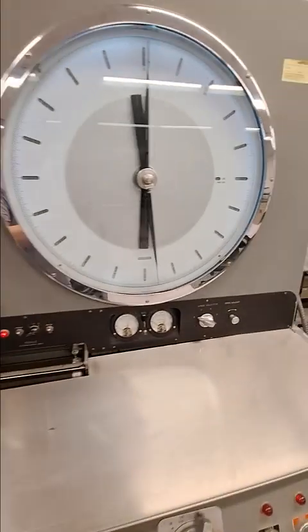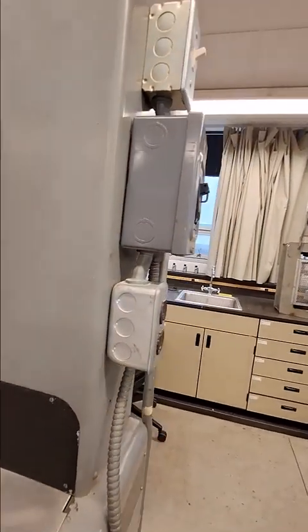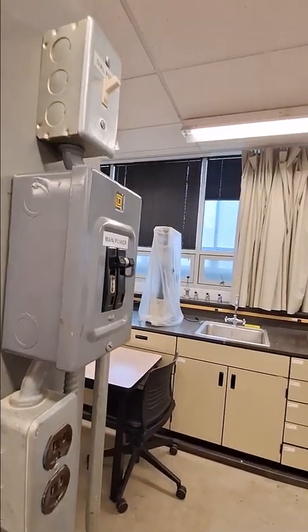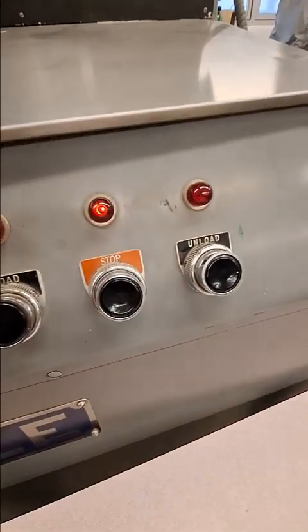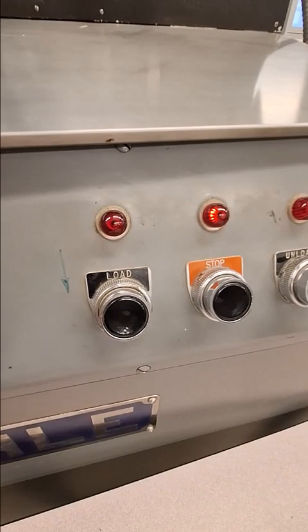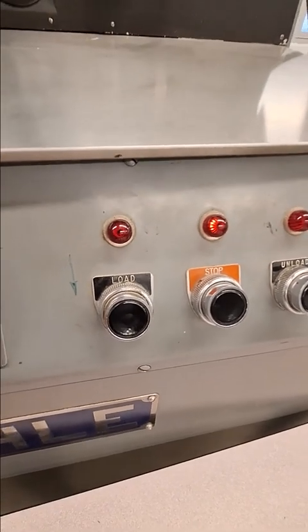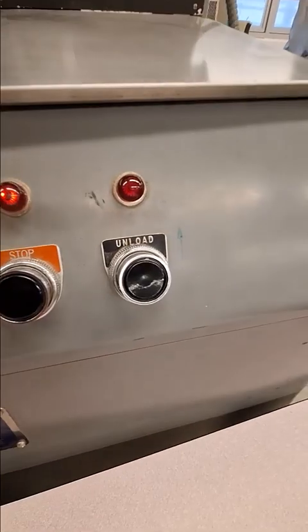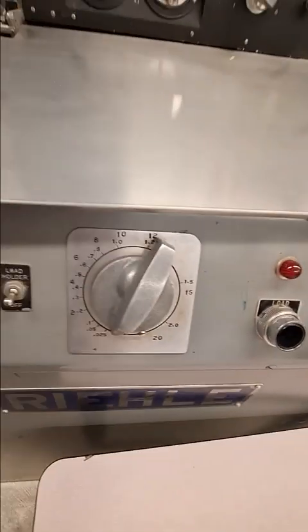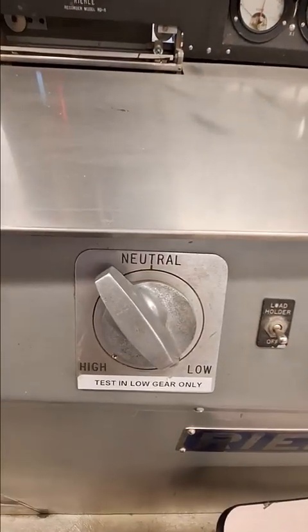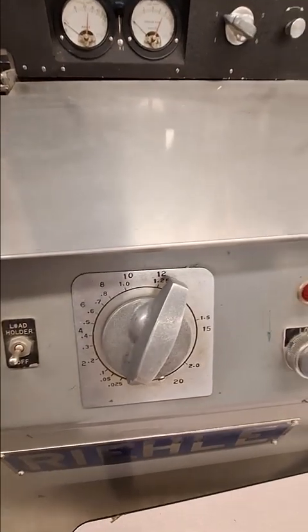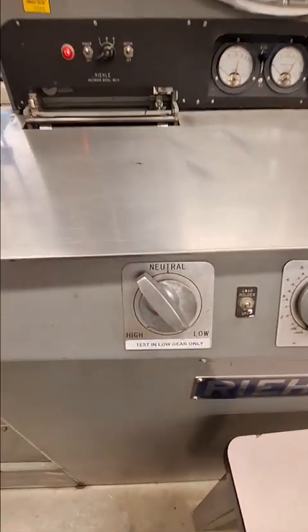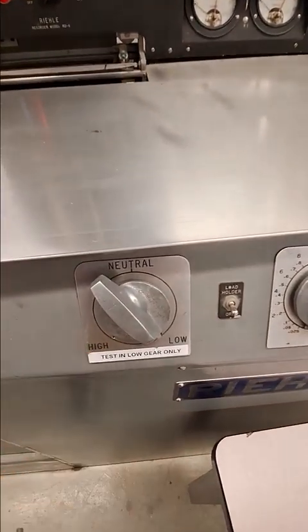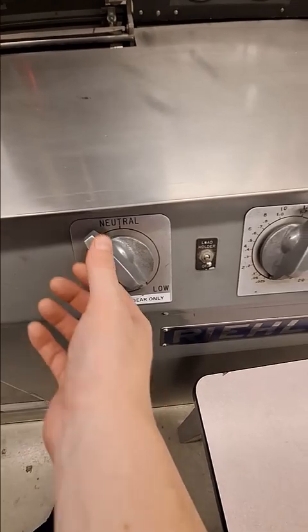So we've powered it up over here. As you can see, we have our dial switch, we have our power on. We have our jog functions. Load will move the grips further apart. Unload will compress the system. We have a low and high strain rate system where we're going to control that strain rate and run at 15 millimeters per minute.